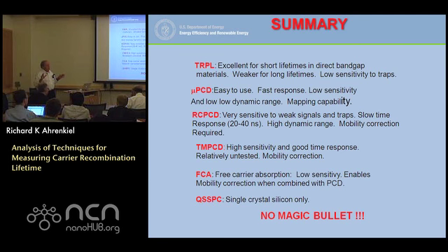So these shapes really contain all the information, and the answer to what is the lifetime? I don't know. It depends on injection level. In reality, if one were looking at all the data, we would do a lifetime versus injection level, assuming the surface and everything else was accounted for. But it is a function of injection level. And we routinely do plotting in MATLAB with that kind of thing, lifetime versus injection level, where we take the shape, the instantaneous slope, and get a lifetime, and if we can calibrate the time axis in terms of injection level, then we plot lifetime versus injection level. So there's no one answer. It's a function of injection level.